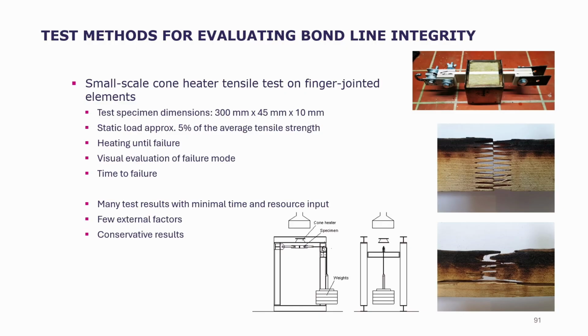So we take a finger-jointed element like this, we put it under static load, heat it, burn it from the top until failure happens, and we measure the time to failure. Also, we look at the failure mode. So still, many tests with minimal time, minimal resource, few external factors, and very conservative results.